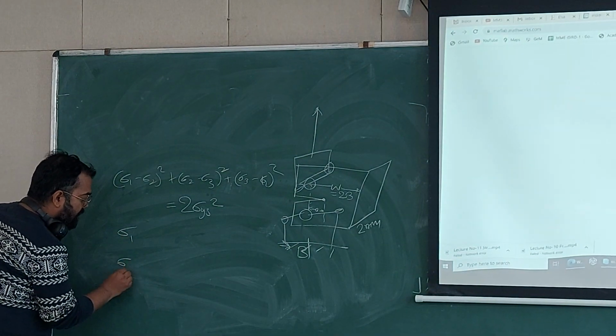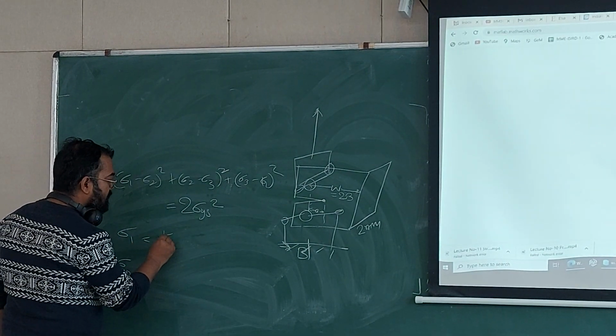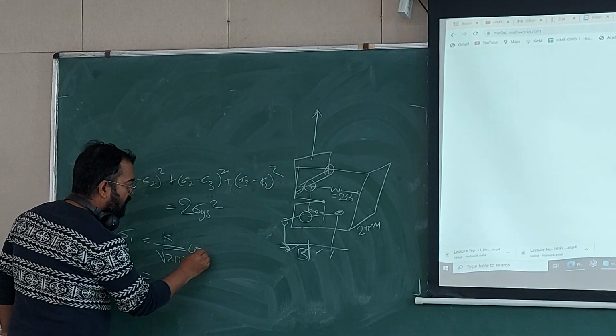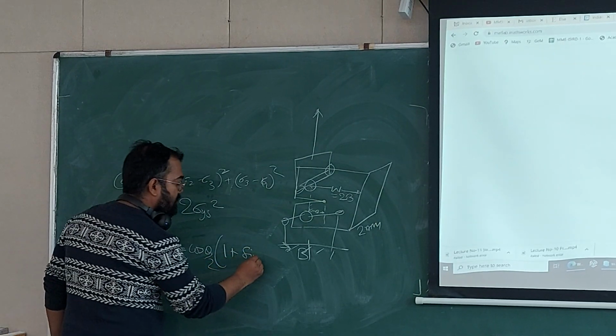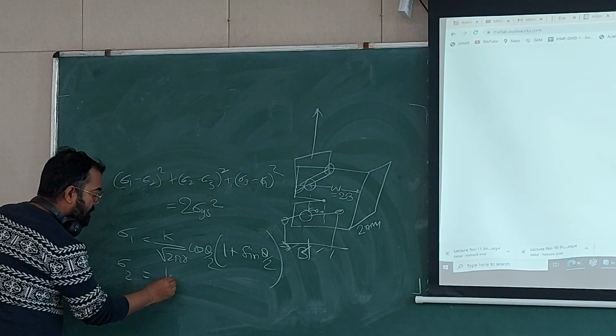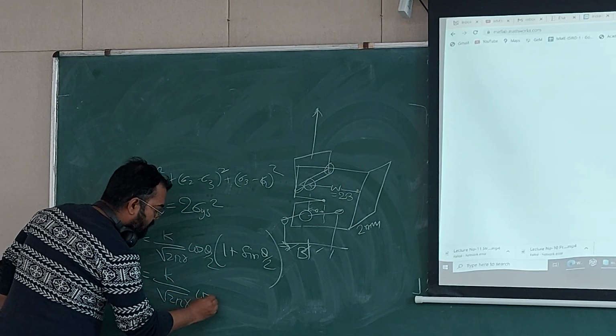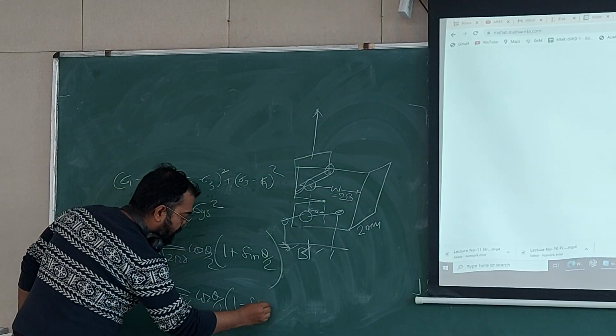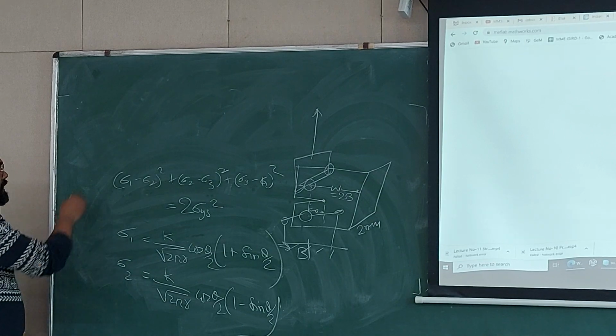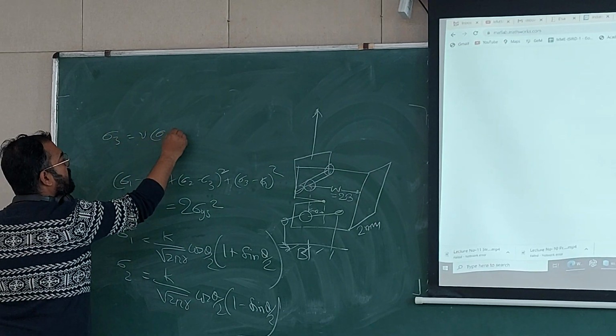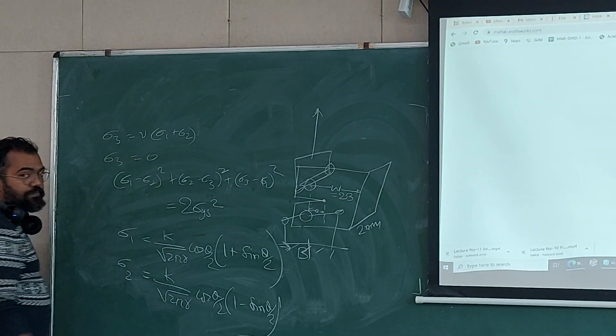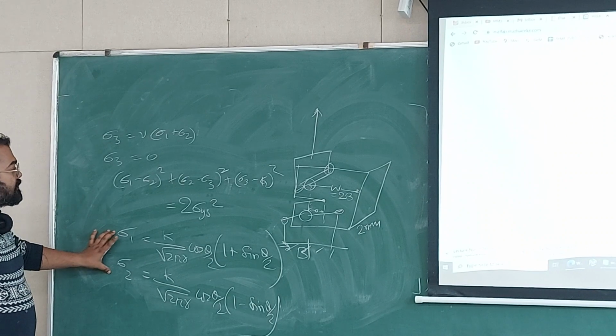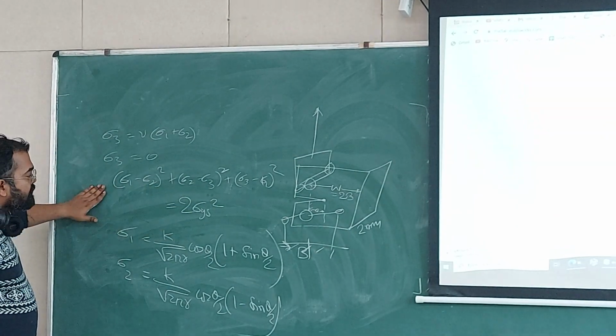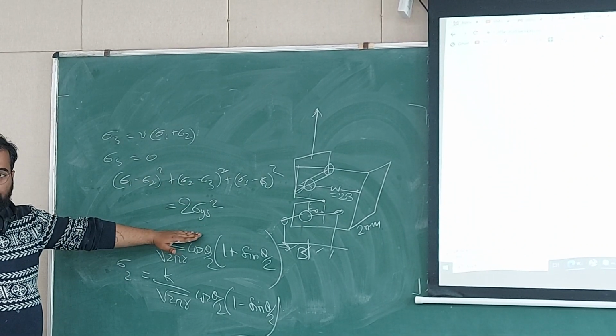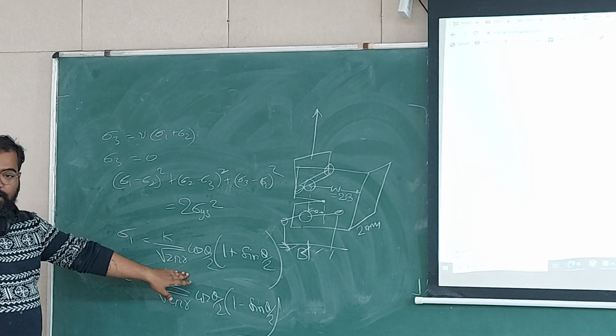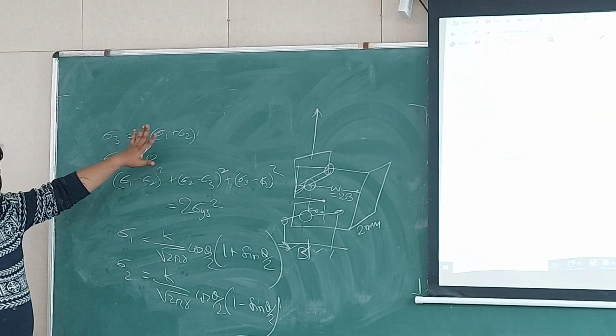And sigma 1, sigma 2 from our Irwin's derivation is K by root 2 pi r, cos theta by 2, 1 plus sine theta by 2, and K by root 2 pi r, cos theta by 2, 1 minus sine theta by 2. And if it is plane strain condition, then sigma 3 will be nu into (sigma 1 plus sigma 2). And if it is plane stress, then this will be 0. Understood? Now you plug the values of these in this equation. So you will have a function of r and theta equal to sigma ys. Sigma 1 is being replaced by a function of r and theta, sigma 2 by r and theta, sigma 3 by r, theta and nu.